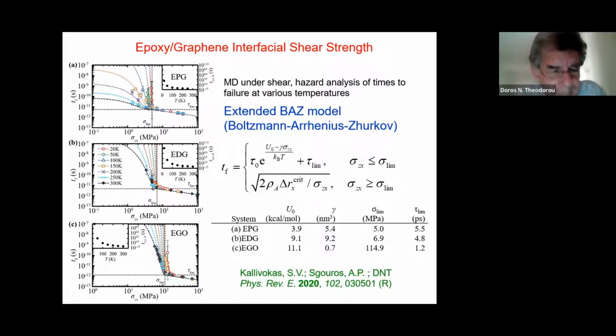Now, one can compare the different types of interfaces in terms of these parameters, the U0 and the gamma. And one sees that the interface between the epoxy and the graphene, the pristine graphene, is quite weak. Its U0 is quite low. If one has defects, and even more, if one has these OH groups, the graphene oxide, this U0 rises, the interface is strengthened, and it is more difficult to destroy it.